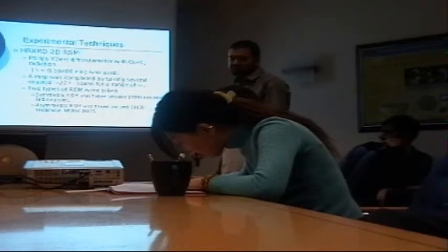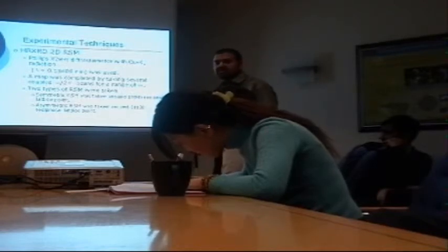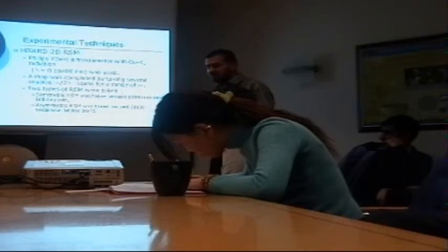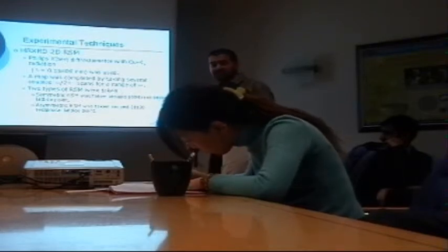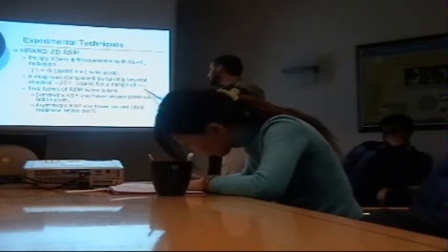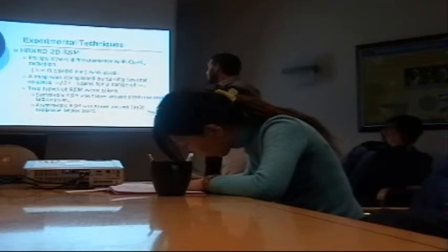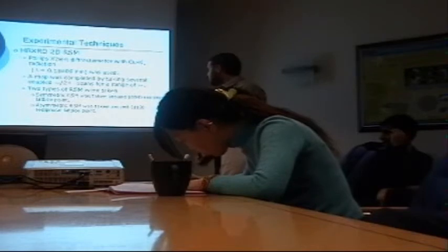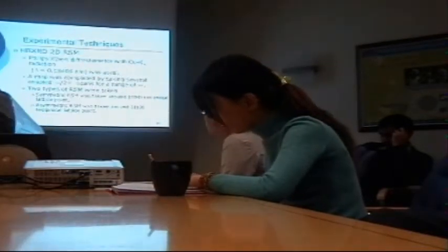First of all, we can see the reflection from the surface in terms of the structure form factor. We will see the reflection from all the surfaces which have Miller indices, in the case of an FCC structure, that are all even or all odd. So we can use those reciprocal space points. And in this case, I can draw it here.